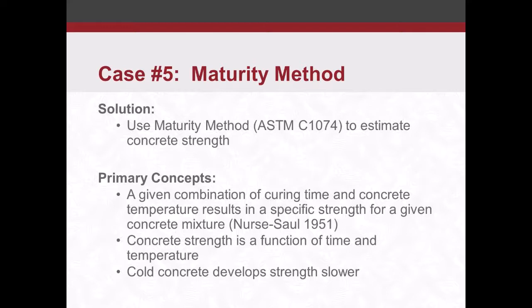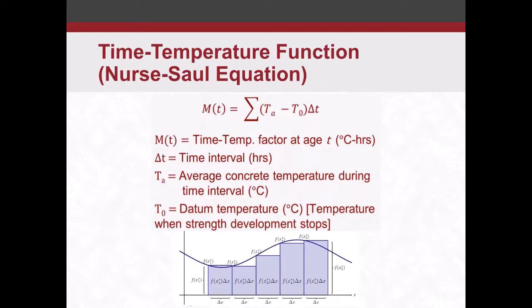We know that, and we also know that cold concrete develops strength a little bit slower. So this is the Nurse-Saul equation that's part of the ASTM. There's actually another maturity equation that's part of the ASTM, but this is the most common one that's used. It's a time-temperature factor. Here in the equation, T sub A is the average concrete temperature during time interval delta T. That time interval can be 1 minute, 15 minutes, or 60 minutes, whatever.